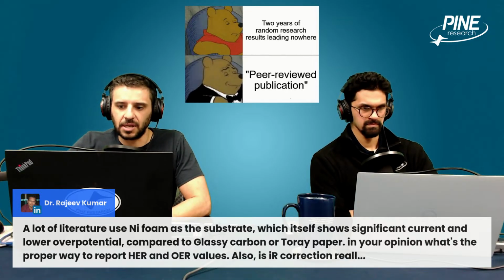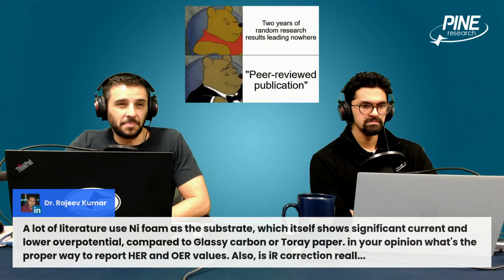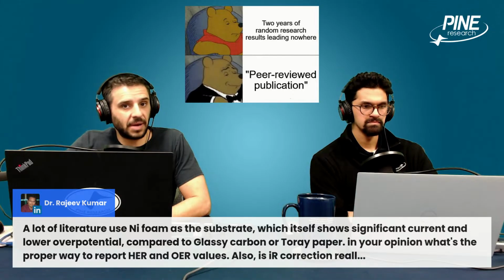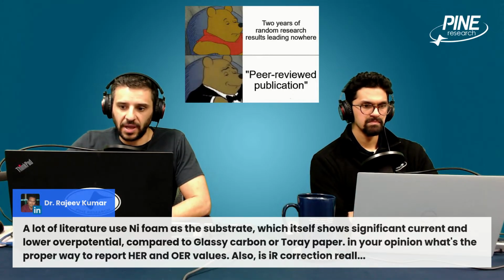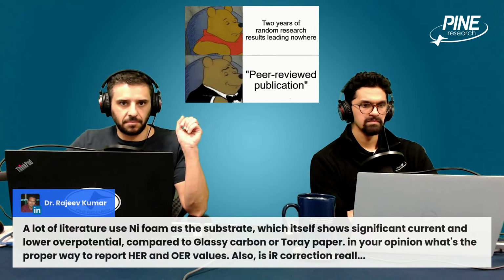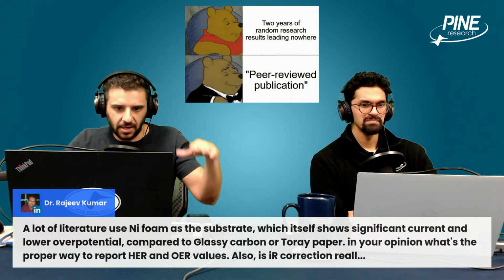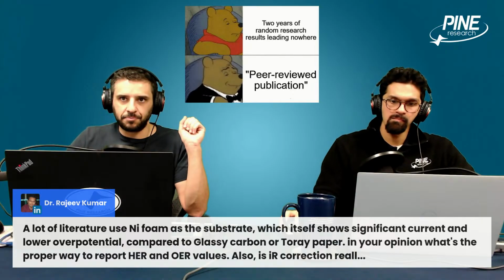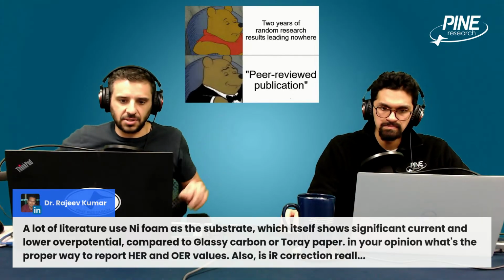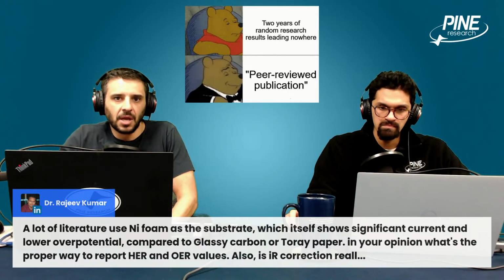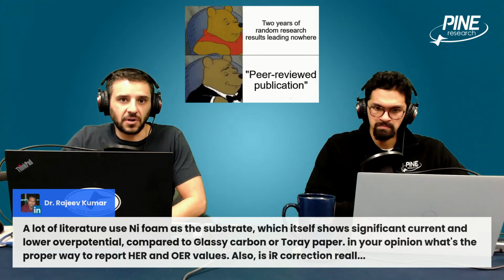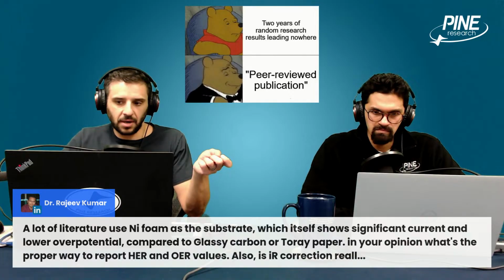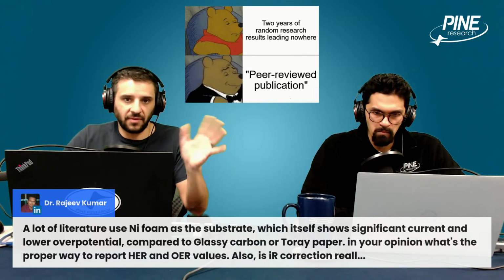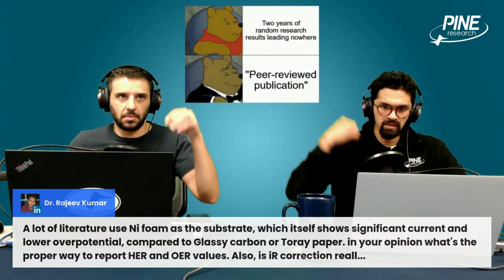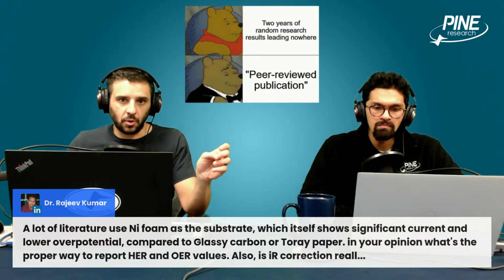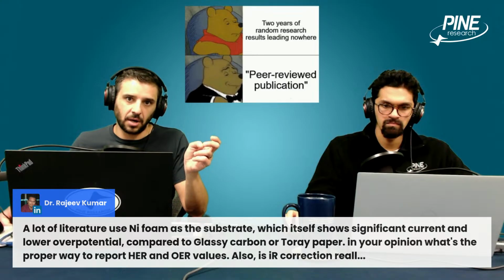So these are some of the reasons why people use it, but you're exactly right that nickel is not the best OER and HER electrocatalyst, but it's definitely better than carbon. And so to your point, I would sort of be a bit reductive here, and I don't mean in an electrochemical way, I mean like in a logical way. I would propose two solutions, and certainly you could have a discussion about other possibilities here. The first, as far as how do you report OER and HER, is that if you're using nickel foam as the substrate, and you're coating it with something, platinum or ruthenium or whatever, is to use a material on the nickel foam that is at least an order of magnitude better catalyst for OER and HER.